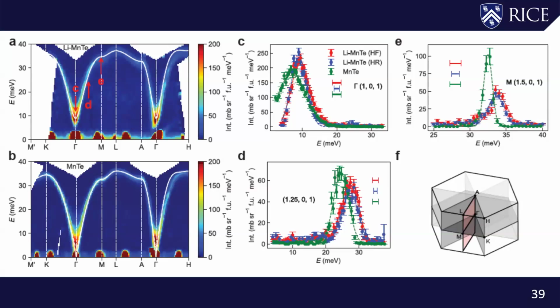But now, if you look at the magnon width in the figure on the upper right, you can see that the magnon width increased by roughly a factor of 2 or 3. This is exceedingly surprising, because in any insulating system, in terms of a Heisenberg model, you should expect that magnon damping should be strictly forbidden, because magnon interactions in local moment systems are exceedingly rare. I mean, we're talking about a collinear system, right? In this case, we find that it becomes much broader, and we speculate that this broadening could be due to the fact that doping lithium into the system induces itinerant and local moment interaction that clearly broadens the spin wave, particularly near the zone boundary.